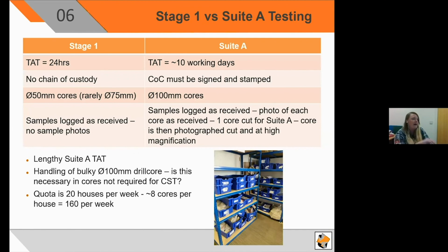So here I've got some comparisons between the stage 1 and the suite A testing. I know we have long turnaround times, which frustrates both the homeowners and the engineers, and I'm hoping this might help you understand why. Our typical turnaround time for Mundic testing is about 24 hours versus the suite A testing, which typically takes 10 days-ish.